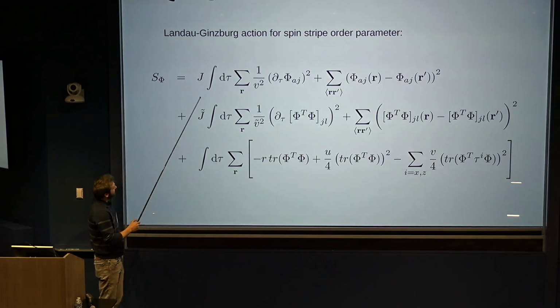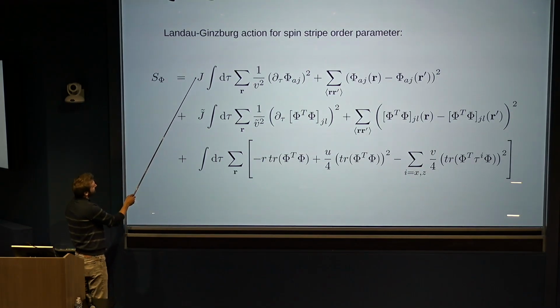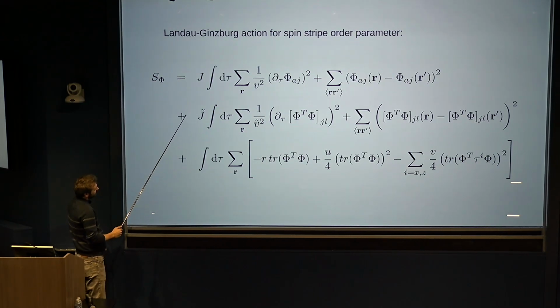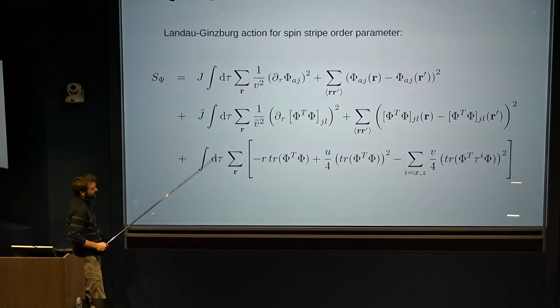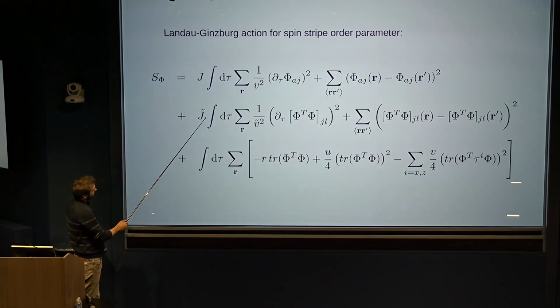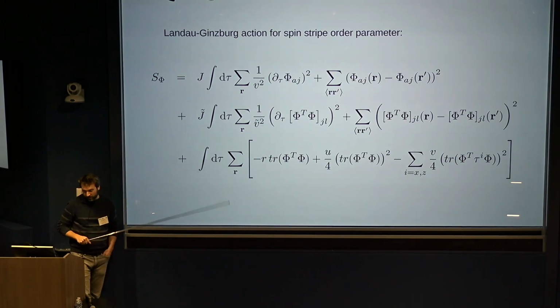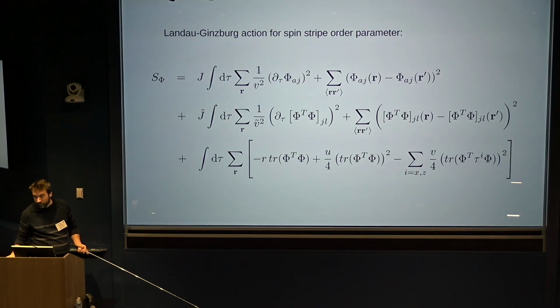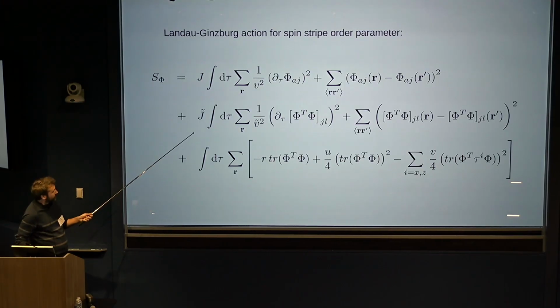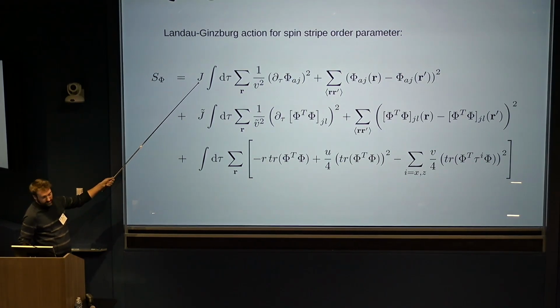So basically this term here, this J, is a stiffness for both charge and spin fluctuations. This J tilde here is a stiffness only for spin fluctuations. And so by adding the J tilde term, I'm making the spin fluctuations stiffer than the charge fluctuations. Okay. And I will now be using this theory with a fixed non-zero J tilde and a fixed field potential, and then vary the stiffness J here.